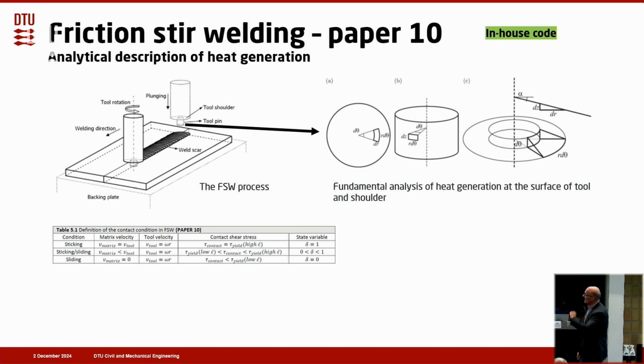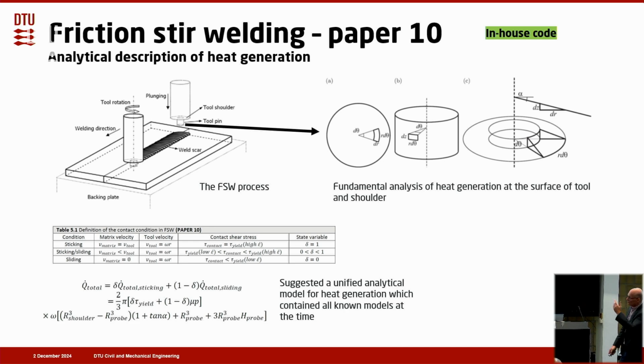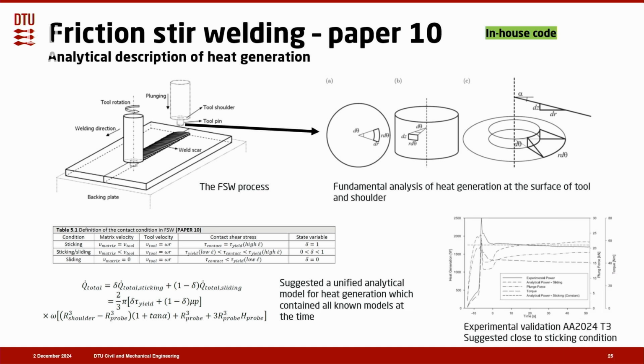So we defined a state variable. It was 1 when there was sticking, because the interface condition is extremely important, 0 when there was sliding, and in between a combination of the two. And then we derived this analytical solution that was a unified model, and it actually contained all the known analytical solutions, special cases at the time. And this was kind of taking them all into account because it was a much more general formulation. It was experimentally validated, and that validation suggested a close to sticking condition.